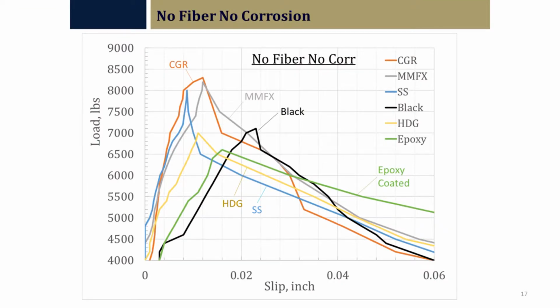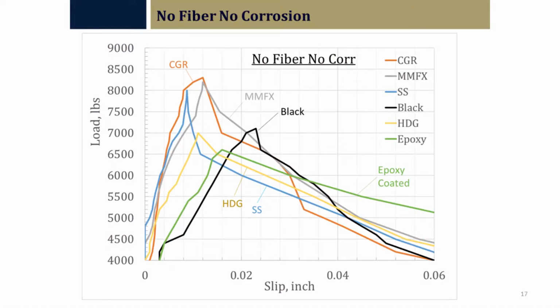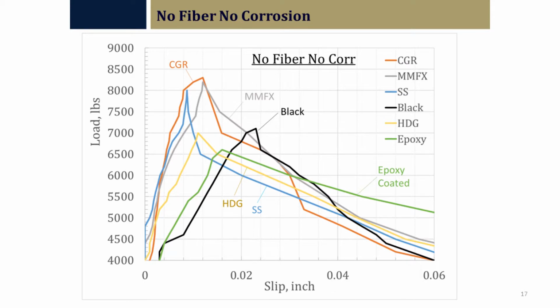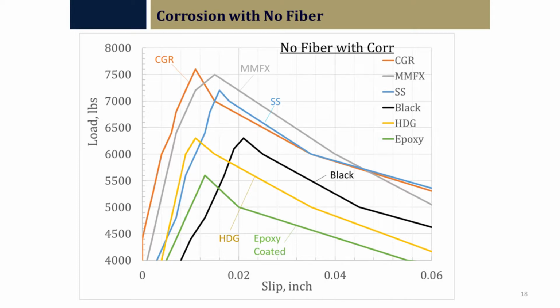And now we're going into the area where no fiber and no corrosion. So no consideration of any fibers in this, but you still have a pretty good result in the pounds over slip. But they're all a little closer, except the traditional hot dip galvanizing is closer to uncoated and epoxy, versus the three, stainless steel, MMFX, and continuous galvanized, are pretty rope tight, around 8,000 pounds and less than 0.02. Adding corrosion with no fiber, again, a little further separation, continuously galvanized and MMFX at the top, stainless steel moving a little bit over to the right, and you can see the results in the rest over top of that.